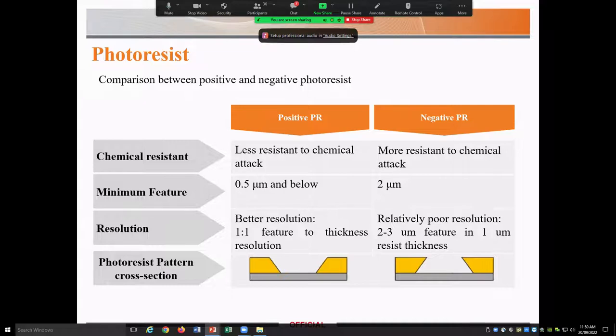Okay, yeah. Because I've previously done a lot of work at ANFF in Queensland, and they do dry film lamination using a negative photoresist, SU-8. There are pros and cons in using these sort of photoresists, the liquid ones and the dry ones. For example, the dry ones may not be as strong when you want to do PDMS casting. But with dry film, you can get very good uniformity, of course. But you're limited to whatever the thickness of that film is.